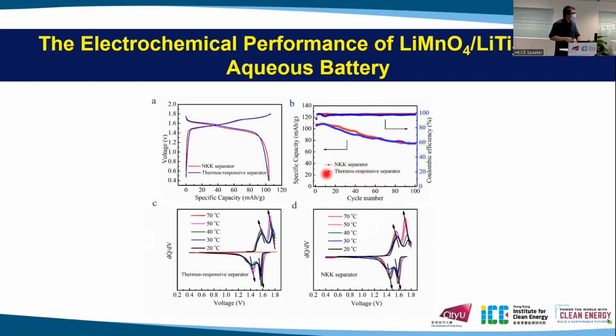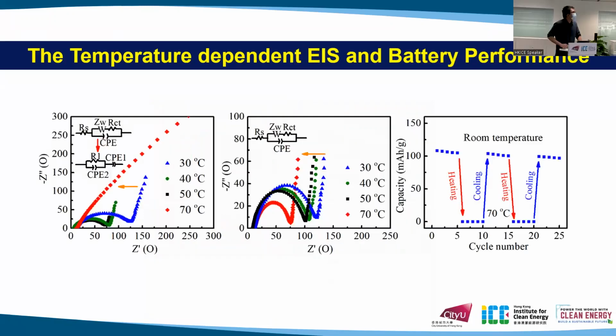And when we vary the operating temperature, we find that the polarization of the battery decreases. It is because at high temperature the ion diffusion resistance will be smaller. But when the temperature increases to 70 degrees Celsius, we find that with the normal separator, it is still the same. But for the one with the thermal responsive separator, there's no current generated, which means that this self-protection works. And this is an EIS indicating that the resistance increased significantly after the temperature increased to 70 degrees. And the most important thing, this change is reversible. We can try it many times, and the battery still works.